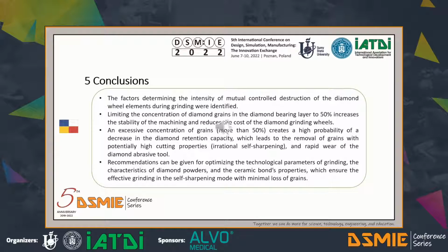And finally, the following main conclusions and recommendations for possible practical use of the results. The factors determining the intensity of mutual controlled destruction of the diamond wheel elements during grinding were identified. An increase in the Young's modulus of their bond leads to an increase in equivalent stresses in the contact zone of the wheel with the process material, and as a result, it contributes to an increase in the efficiency of the process. Limiting the concentration of diamond grains in the diamond-bearing layer to 50% increases the stability of the machining and reduces the cost of the diamond grinding wheels.